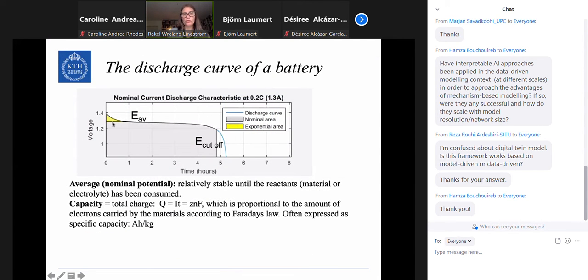So typically a discharge curve looks like this. We have an average potential, which in reality is slightly lower than what we theoretically have shown. But that is quite stable as long as we have material, and then when we have used up the material, it drops. And the capacity of the cell is then the charge, the integral of this curve. So it is the current that we use for discharge times the time. And that is equal then to the Faraday constant times the number of moles and the electrons. So this can be calculated also theoretically.